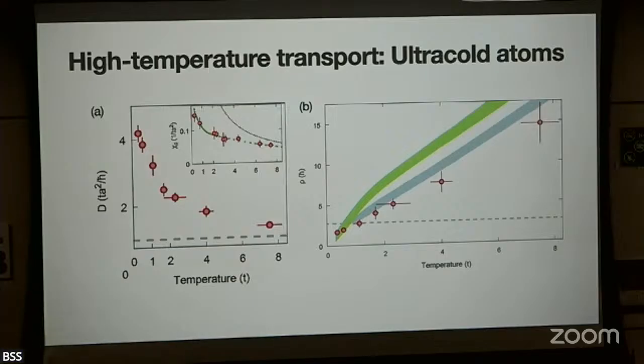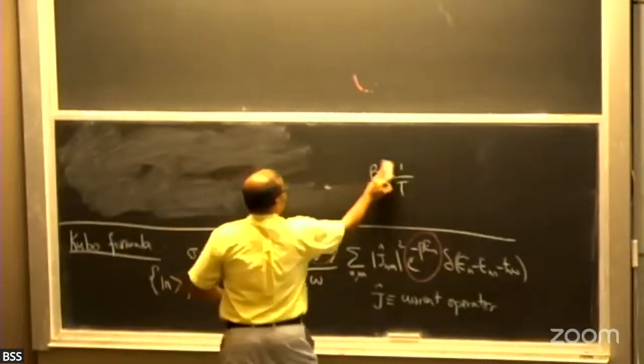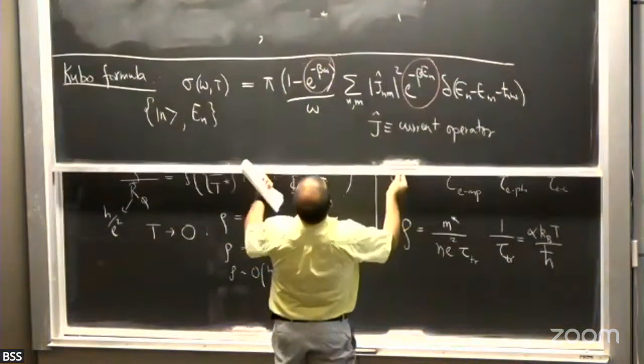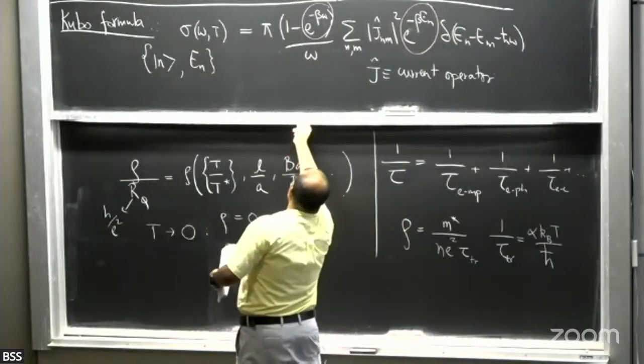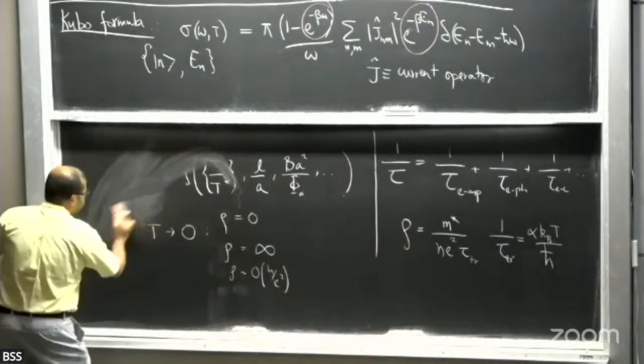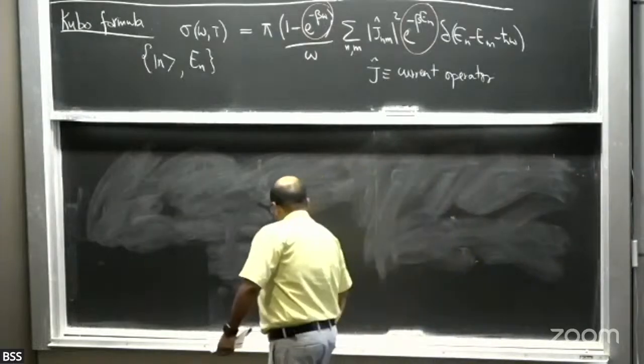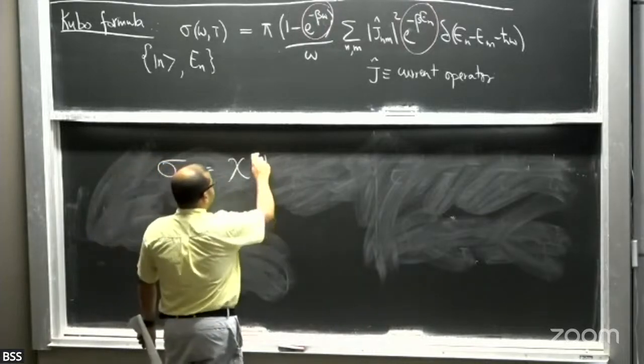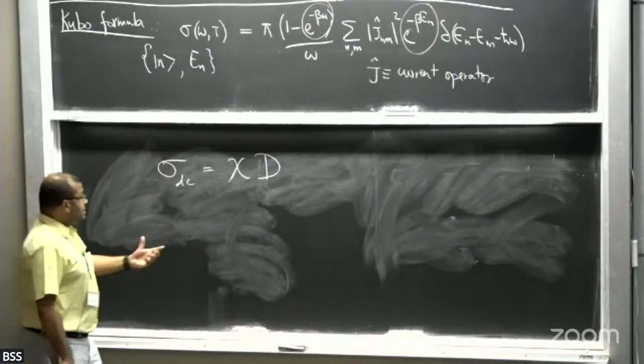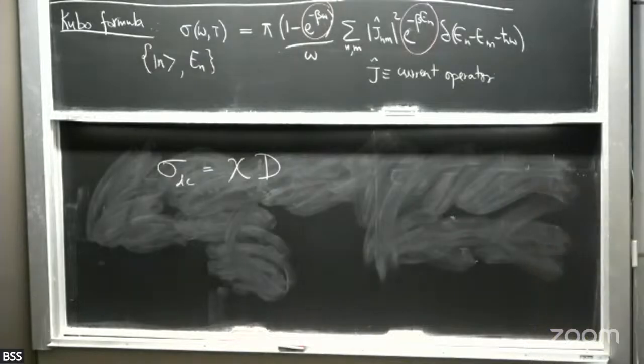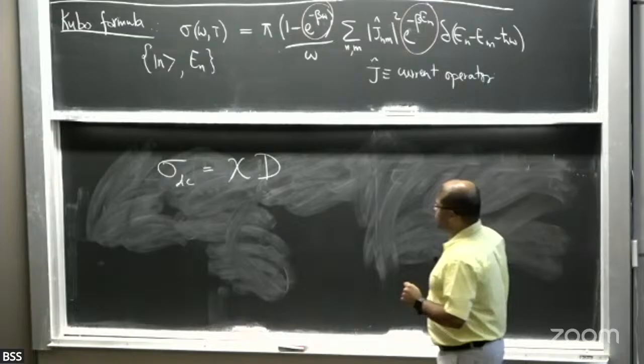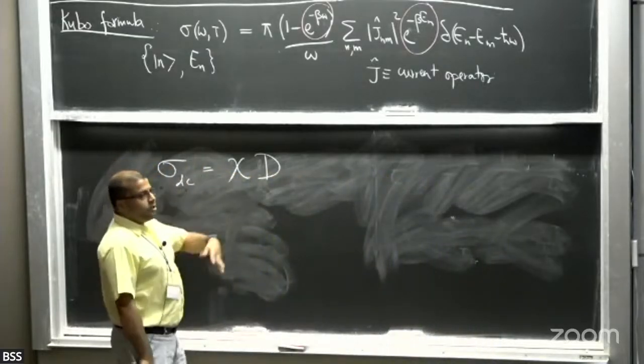And then what you do in order to get a resistivity is go back to the basics. Use Einstein relations that relate all of these three quantities. Okay, so now I'm going to ignore what are known as any thermoelectric effects. So in that limit, the conductivity, the DC conductivity, is related to the charge compressibility times the diffusion coefficient. Okay, and what's done in the experiment is that they have a way to extract the diffusion coefficient as a function of temperature and the compressibility as a function of temperature. And they use that to figure out what the conductivity or relatedly the resistivity should be.